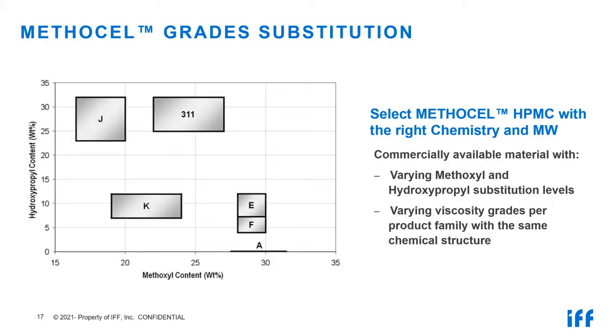If you make a graph presenting the methoxylation content and the hydroxypropylation content on the 2 axes, you will get some boxes, and these boxes represent the specification windows of our cellulose ethers. And you can see very far below there is also the A class, but it is just a line, it's not a box. The reason, I said already, is that METHOCEL A is a pure methyl cellulose, and of course the hydroxypropylation content is 0. That's the reason why it is just a line. Next slide.